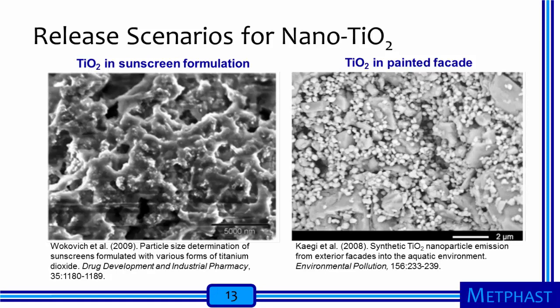The image on the right from Kaegi and co-authors shows a surface covered with a paint that contains titanium dioxide nanoparticles. The particles are spread across the surface relatively evenly, and they are not highly agglomerated. In addition, they appear to be accessible to the atmosphere, leading to the potential for removal from the surface during precipitation events. The nanoparticles could then move with runoff into stormwater systems, surface waters, or soil.